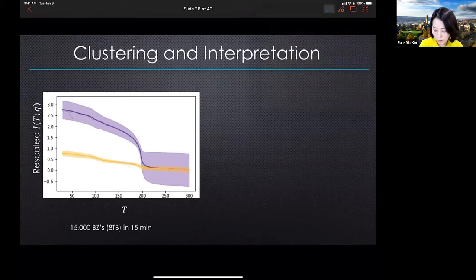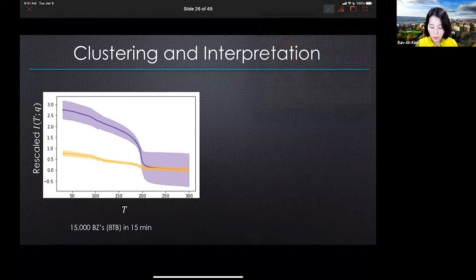This behavior here is very familiar looking, sort of order parameter looking behavior. For XTEC, what we set is the number of clusters. That's the only thing we set. We tried with 2 clusters here, and we found one of them to have a clear onset that looks like an order parameter. I emphasize the importance of interpretation for this approach.